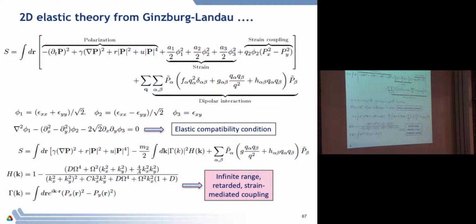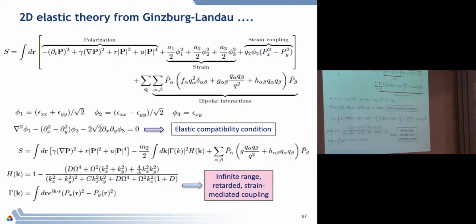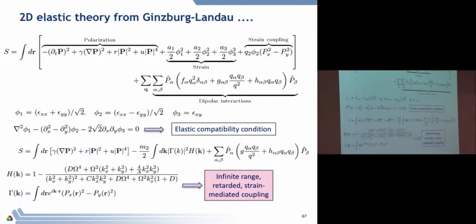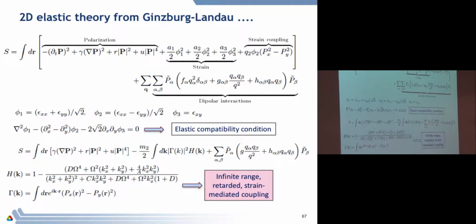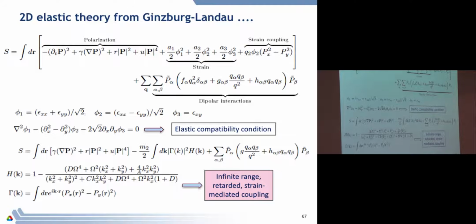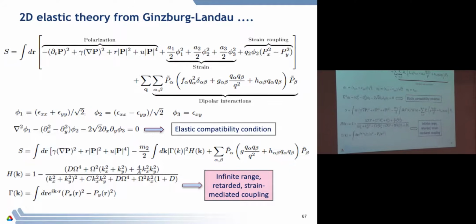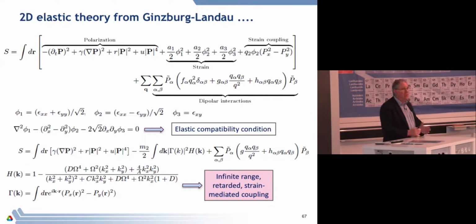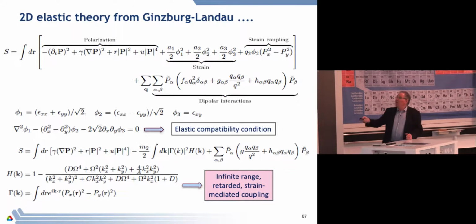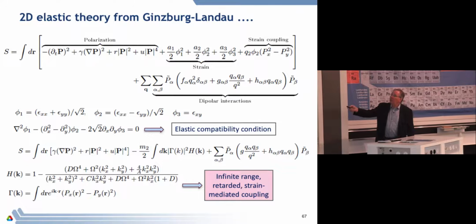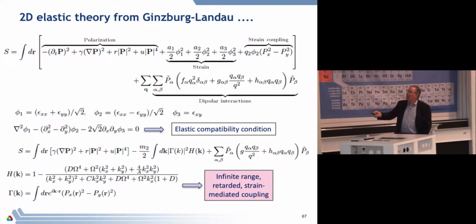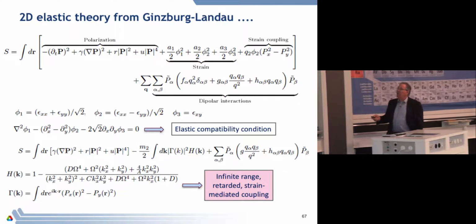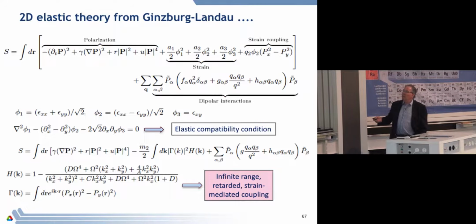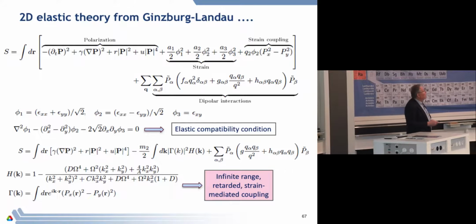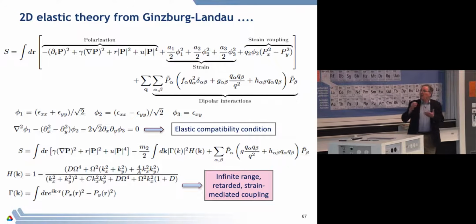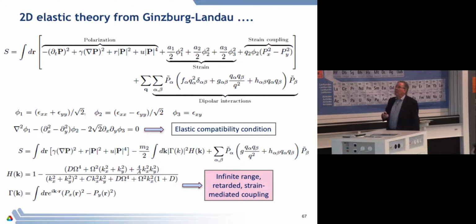Okay. Now, one very important thing about elasticity theory is, we like to write elasticity in terms of these three independent fields in 2 dimensions, but that's actually one too many. Because if you want to describe the deformation of a sheet in 2 dimensions, it clearly only requires a 2-dimensional vector field, and I've got too many degrees of freedom here. Okay? So these are not independent. Okay? They are related by what's known as an elastic compatibility condition. And it has a sort of a Poisson equation-like form. It says that fluctuations in one field have to be cancelled by fluctuations in the other. And all that's just making sure of is it's making sure that things don't tear when you deform it.